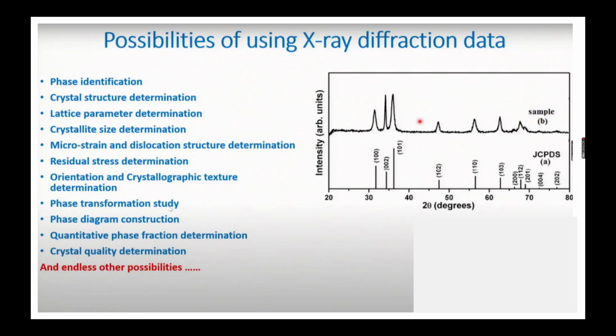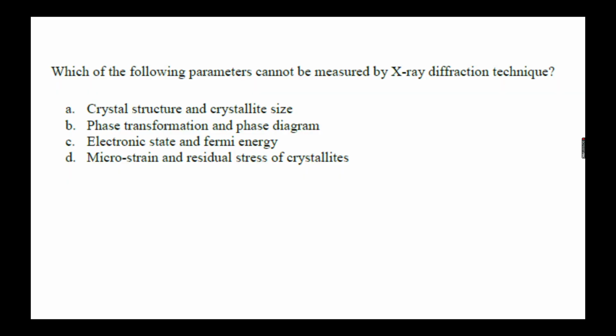Phase transformation study we can do, because all of this affects your peaks in some way, so we can say this is due to this factor. Phase diagram construction, quantitative phase fraction determination, crystal quality determination, and others. So we can extract so much knowledge from your XRD data. But one thing that we can't do is the electronic state and the Fermi energy. This is something else, and from XRD we cannot measure it. So the answer is C.